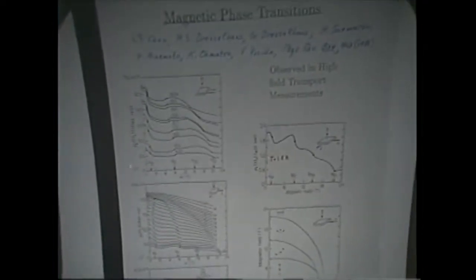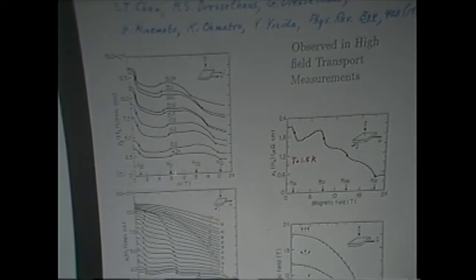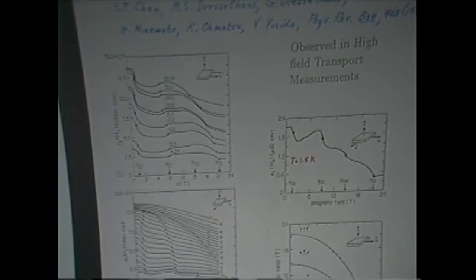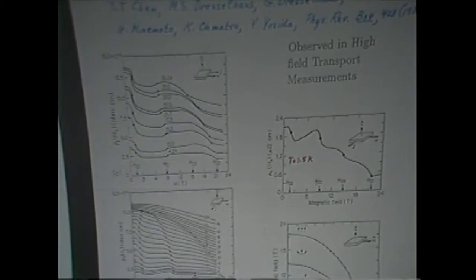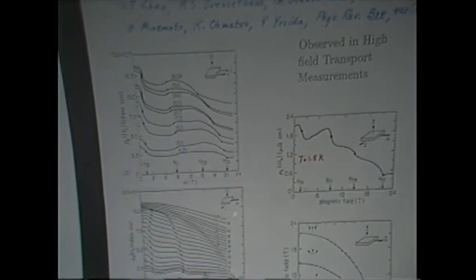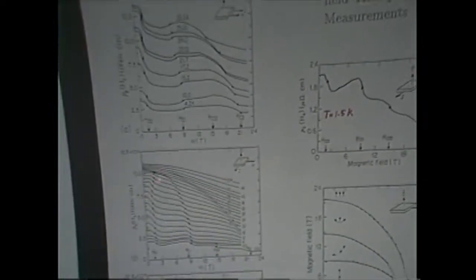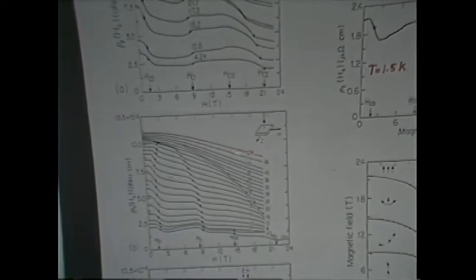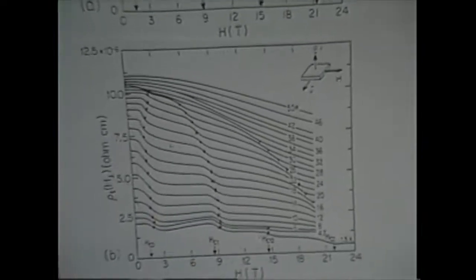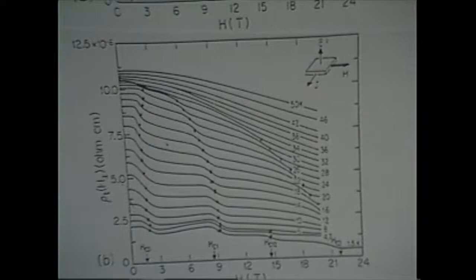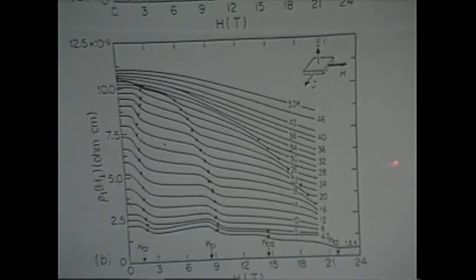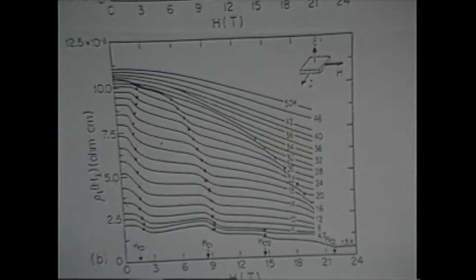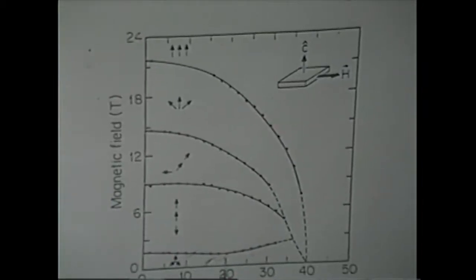Here we have transport properties, resistivity, as a function of magnetic field. And you see glitches. You see big changes occurring as a function of magnetic field. Each of these glitches, I put a little red dot, shows a magnetic phase transition. And this one here in particular, this is the c-axis magnetic field and current directions. You could see that what we're plotting here is different temperatures. Each scan is taken at a different temperature. And you can almost see the magnetic phase diagram pop out at you just by looking at the transport data. Well, taking each of these temperature sweeps, and this is temperature here, and going up in temperature, just make dots for all of these things, and you develop a magnetic phase diagram.